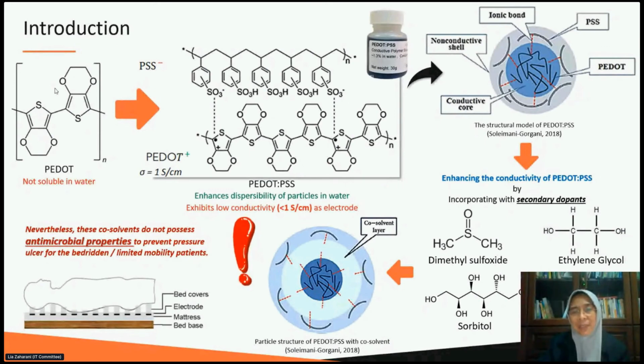Adding organic co-solvent in the ink formulation may bring a screening effect between the positively charged PEDOT chains and negatively charged PSS chains, reducing the Coulomb interaction between them, which causes a phase separation between PEDOT and PSS. Nevertheless, this co-solvent does not possess antimicrobial properties to prevent pressure ulcers in bedridden or limited mobility patients. So a material needs to be added that has the advantage of antimicrobial properties.